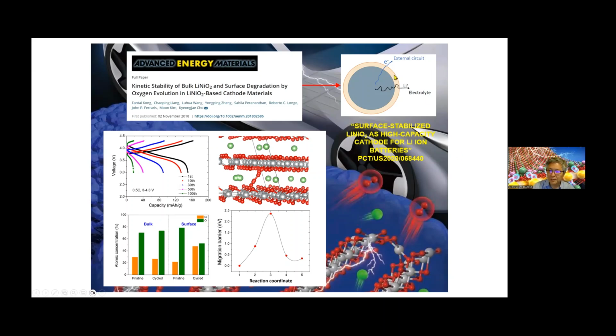if we can protect the surface. So we have developed a surface stabilization scheme that, by having an oxide coating, we protect the surface and suppress this nickel monoxide formation and oxygen evolution. We can stabilize this and actually suppress this battery degradation and the safety problem.